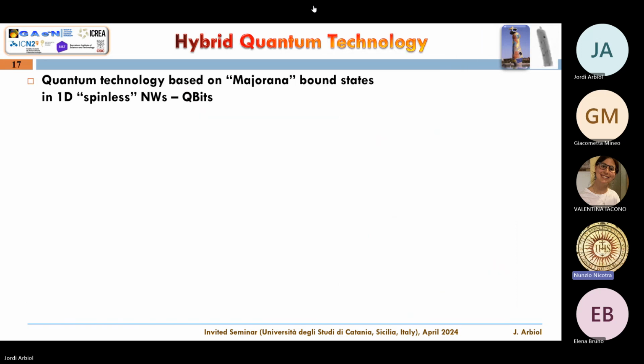Of course, we then analyze these nanowires, and you had a perfect ballistic regime, so meaning that quantum properties were arising from this material because it was perfect. At the end, you had only one twin boundary, which was on the side of the material. And if you avoid that side, the rest of the material has no strain. So it's growing without defects and perfectly attached to the substrate. So you can remove it and just contact it. And then let's go for Majorana.